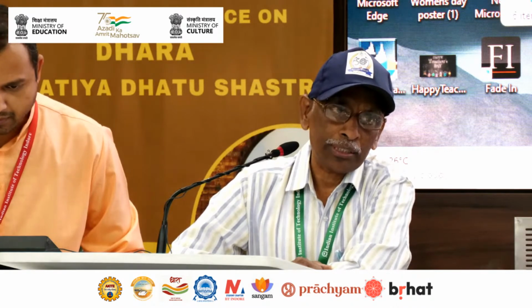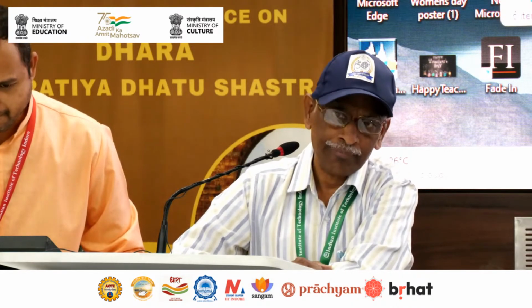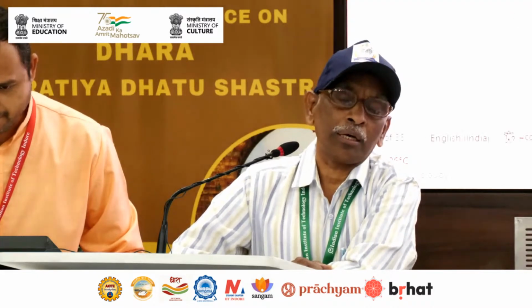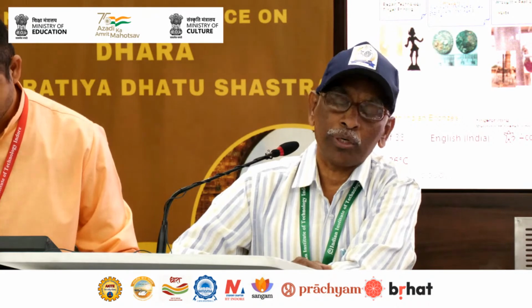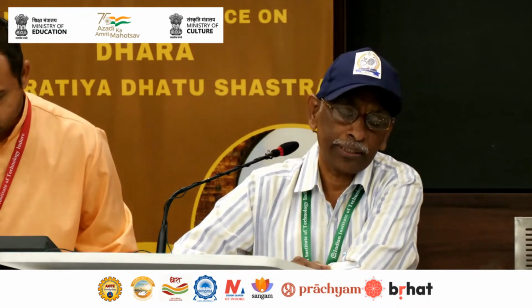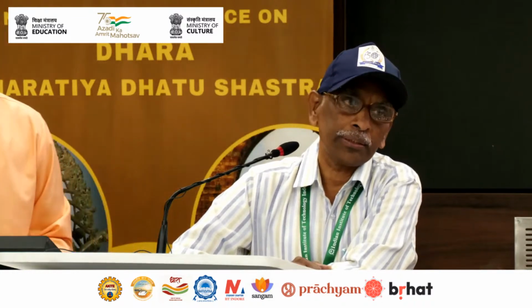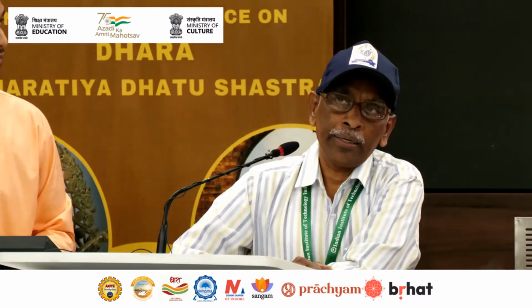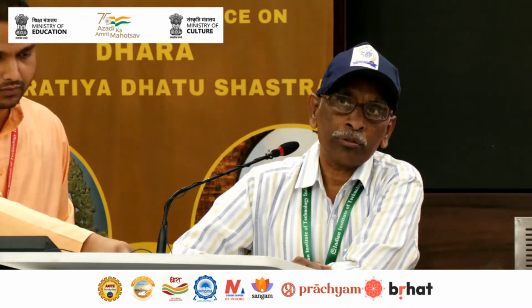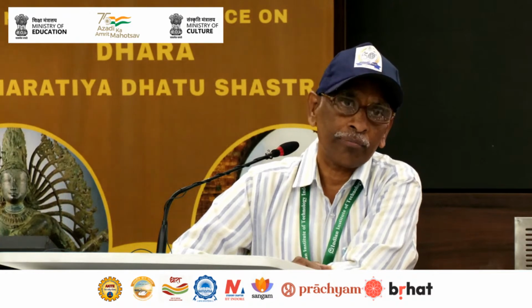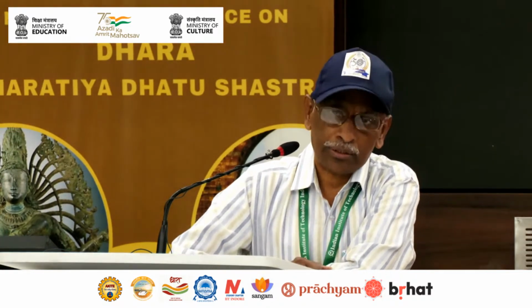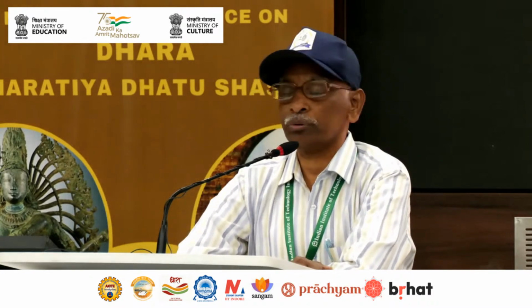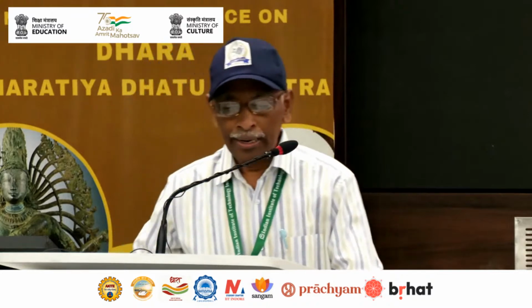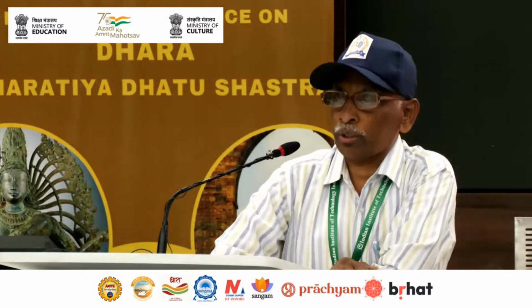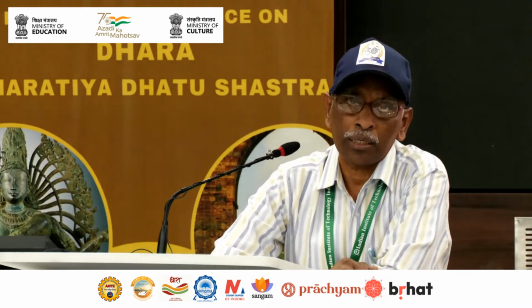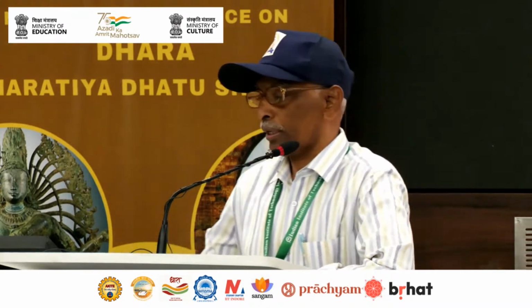In one case, we demonstrate that the pillar is made in the horizontal fashion, and also the interlocking of the lumps which are made in small quantities. Some time back it was told 5 to 6 kg, but we believe that this may be around 20 kgs in the case of Delhi iron pillar. And also, we take that the locking mechanism is taken from the natural rock structures. So this is one aspect which we would like to bring out. And also in the Delhi iron pillar, we feel that there is gold at one of the regions. That also I will show you, how we have interpreted this.